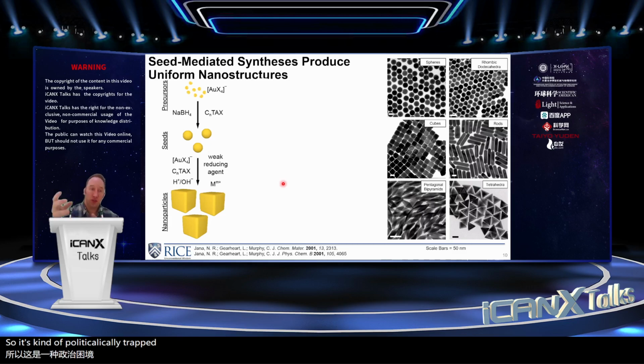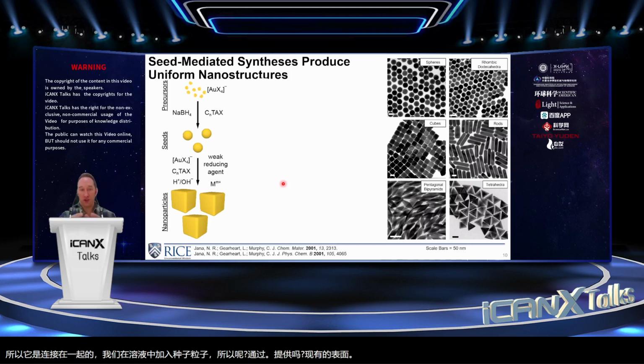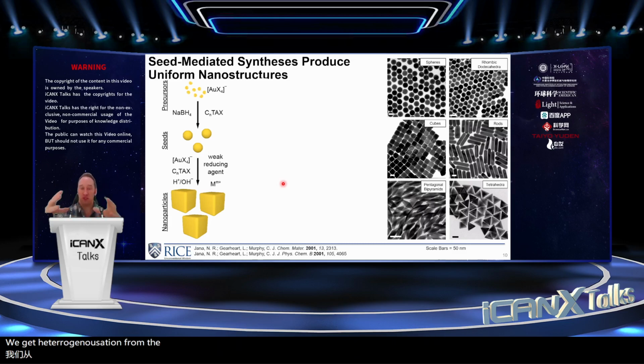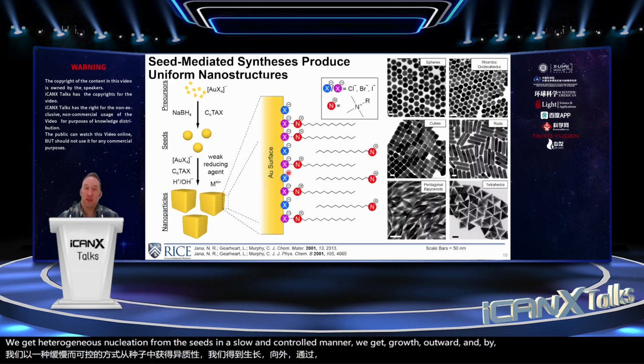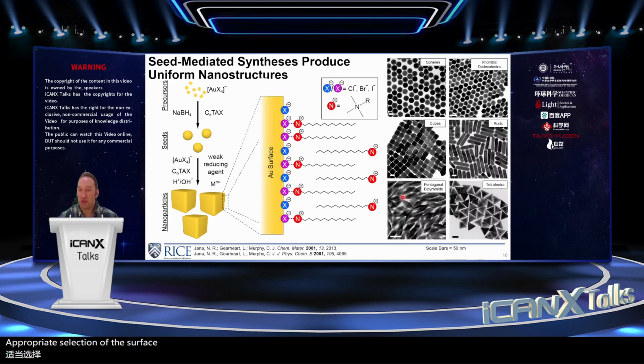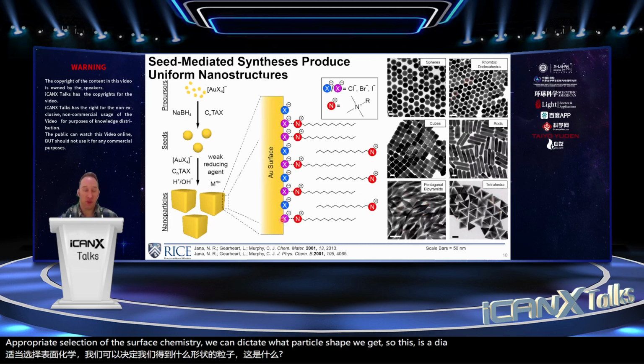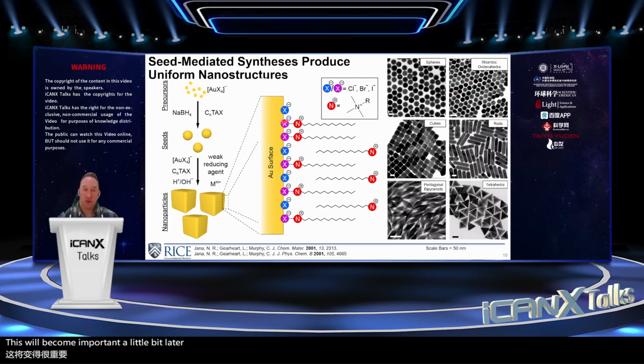And it is to that solution that we add the seed particles. So by providing existing surface, we get heterogeneous nucleation from the seeds in a slow and controlled manner. We get growth outward, and by appropriate selection of the surface chemistry, we can dictate what particle shape we get. So this is a diagram of what the surface is thought to look like. This will become important a little bit later. We have halides that are bound directly to the surface.